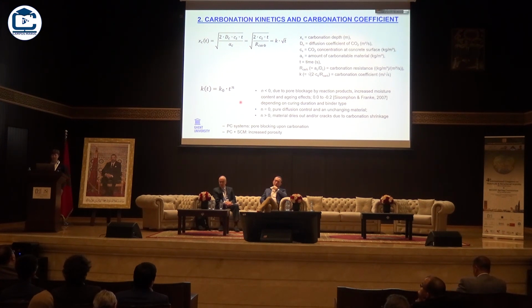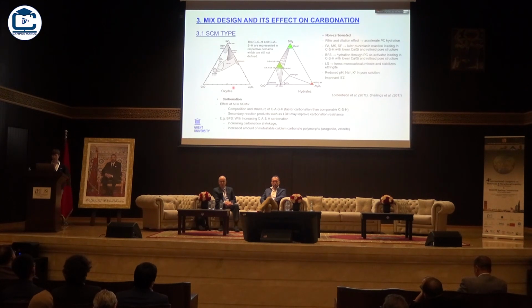On the other hand, if you have, for instance, carbonation shrinkage and crack formation, then the exponent here will be larger than 0. And what we often see is that in Portland cement systems, carbonation is indeed resulting in pore blockage, but if supplementary cementitious materials are present, it might lead to an increased porosity because you more rapidly start to carbonate the calcium silicate hydrates.